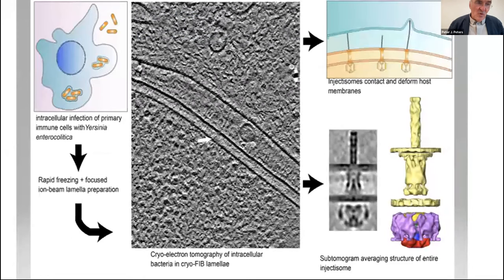We did this with cells that grow on gold grids. These cells were, before they were vitrified, cultured in the presence of bacteria. These bacteria were taken up by the cell. And so you have inside white blood cells that phagocytose these bacteria, deep inside. And then we wanted to study those bacteria in the context of the membrane inside the cell. We gave the cells not only bacteria, but also gold particles, BSA coupled to gold, so a protein coupled to gold. And these gold particles were also endocytosed and phagocytosed. They are present all over the cell in all the endosomes, and they are later used to align the tomogram.